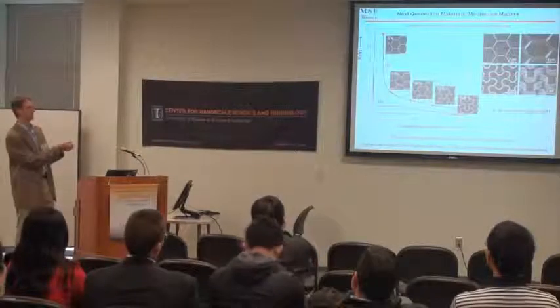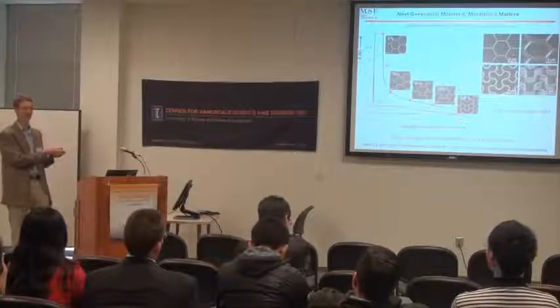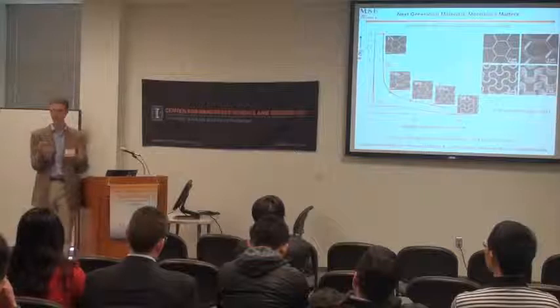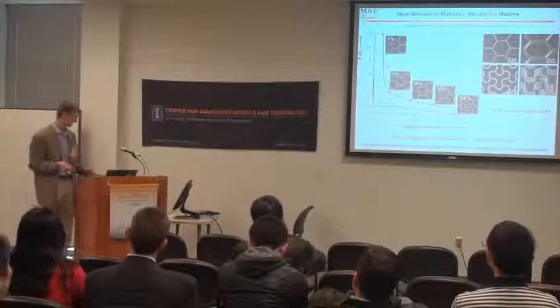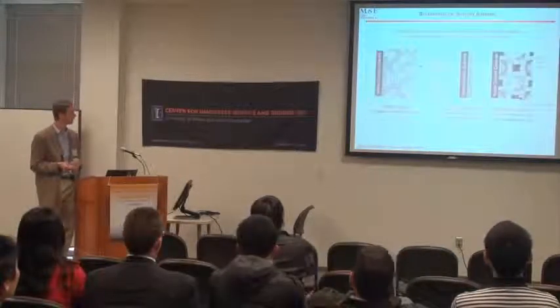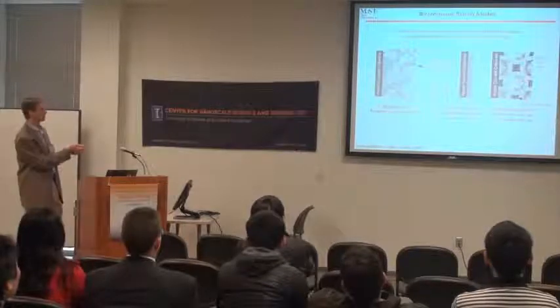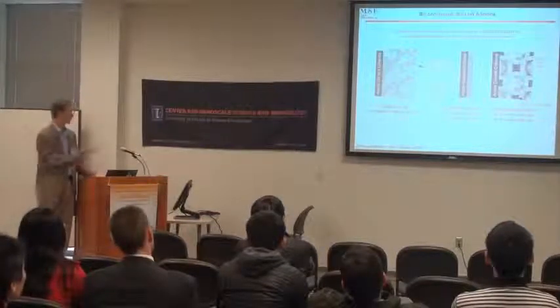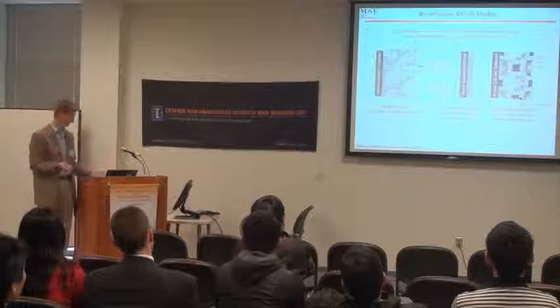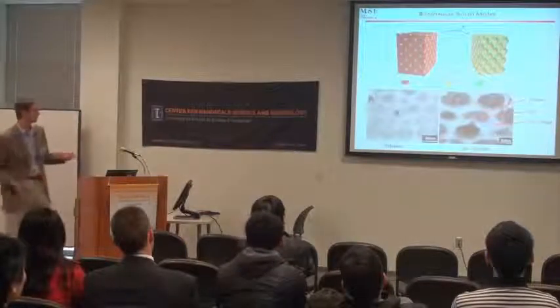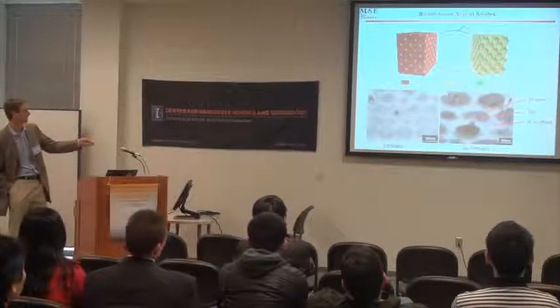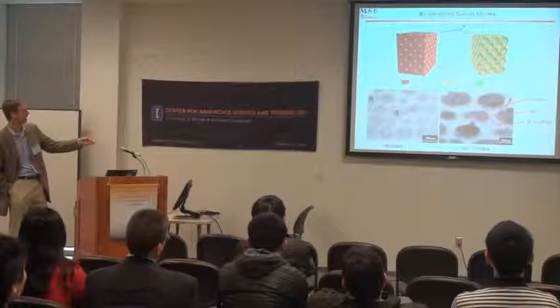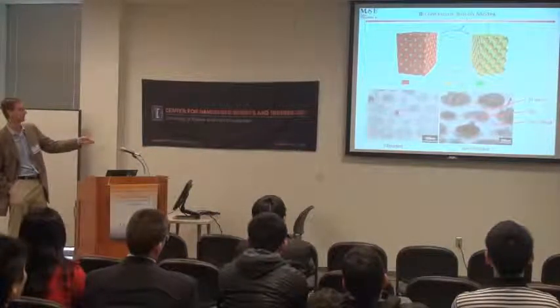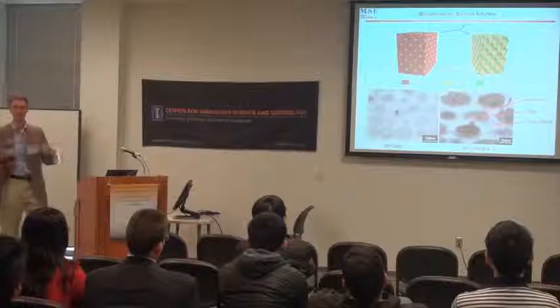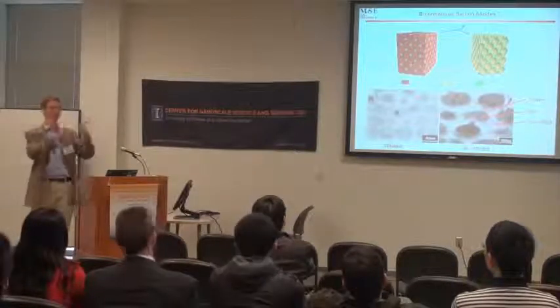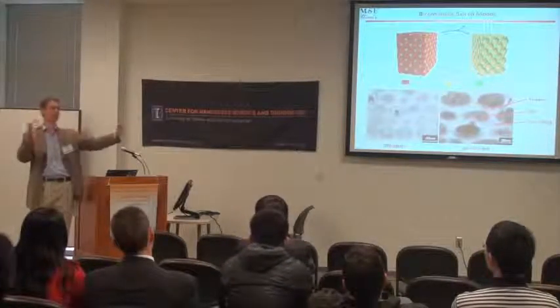And so this only solves half the problem. The other half of the problem is one that has yet to be solved by anybody, but there are some interesting efforts going on. And so we went ahead and did a similar structure using silicon. The pictures look the same, the physics is the same. And what we find here is that the silicon is only present as a thin film. It completely fills the pores when it lithiates and then shrinks back up against the walls when it delithiates. So this is a way that we can overcome the swelling problem.